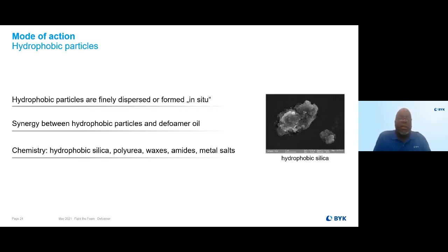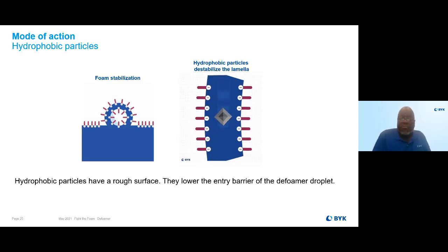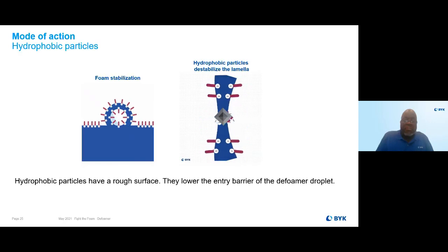And while we still get the effects of the oil, the added particles give it more stability, faster break time, and more permanent results. This is known as pin effect, which creates faster defoaming.